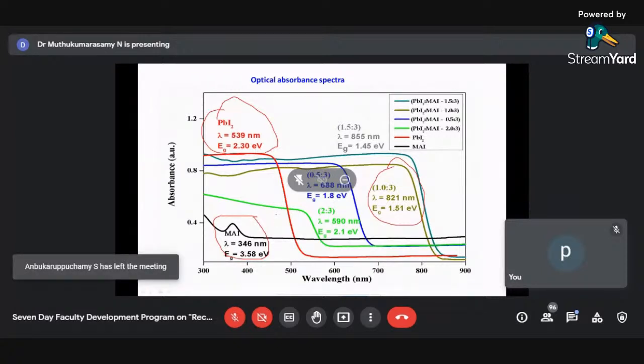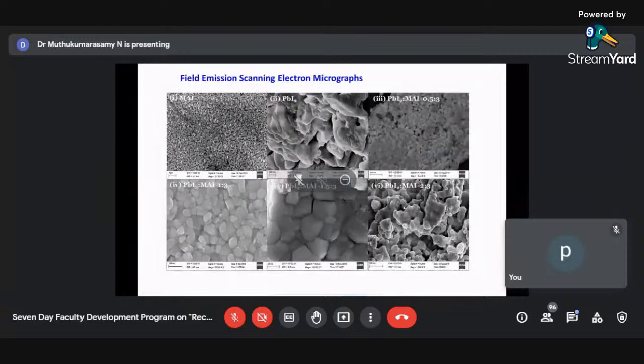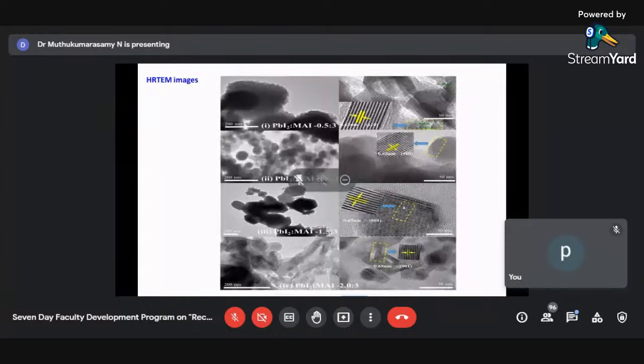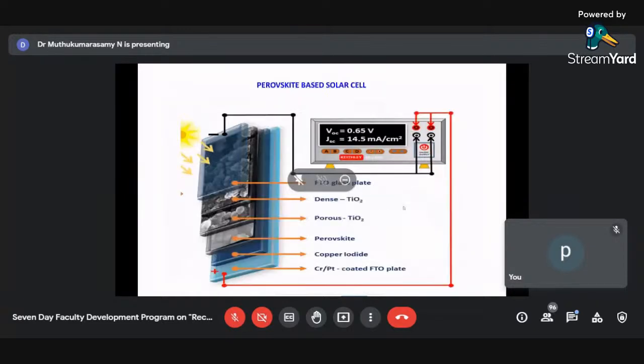But when we mixed methylammonium iodide and lead iodide, you can see when the ratio was 1:3, the window extending up to 800 nanometer, covering the entire visible region. So it will be able to absorb all the visible radiation. And we fabricated, and these are some of the field emission scanning electron microscope images. I'm not going to spend much time on all these things, because many of you may be aware of them. For a particular percentage of lead iodide, we are able to get uniform distribution of our crystallites, and these are HRTEM images, particle size.